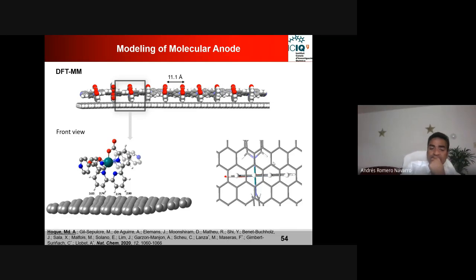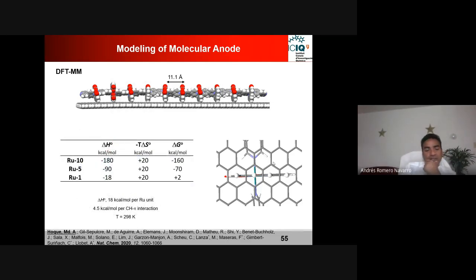So we did this calculation, and what we found is that if we have this Ru1, the mononuclear compound, because of this 4 CH bond interaction, the enthalpic energy is negative. That is a favorable process, but it has this entropy value which is positive. For one molecule, this entropy value is 20 kcal per mole. So if we calculate this delta G value, it is coming positive 2 kcal per mole.